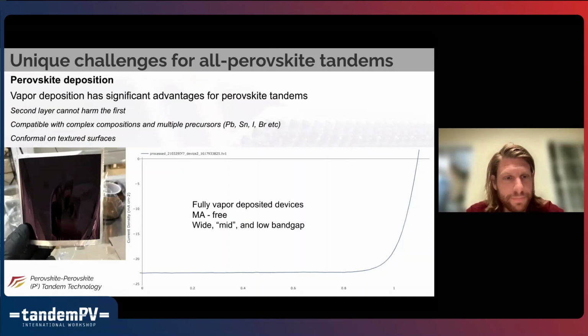standpoint. And then on the left is a fun picture because we're working on plastics, on flexible substrates. You can make these very pretty samples. It's just a little demo, and that's actually extremely thin. We're targeting power densities in the thousands of watts per kilogram, which is impossible with any wafer-based technology. You need a really thin total cell, which is dominated then, of course, by the plastic encapsulant.